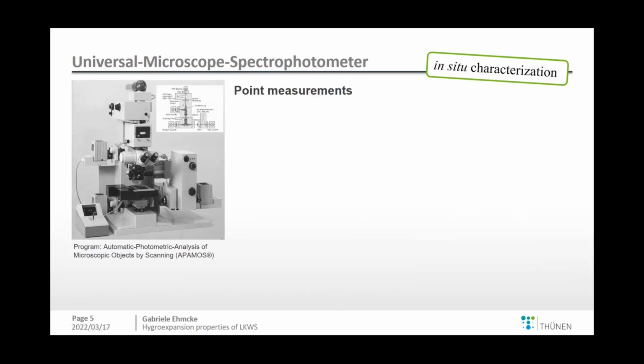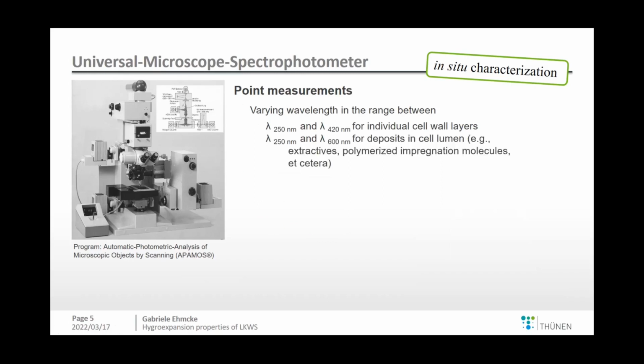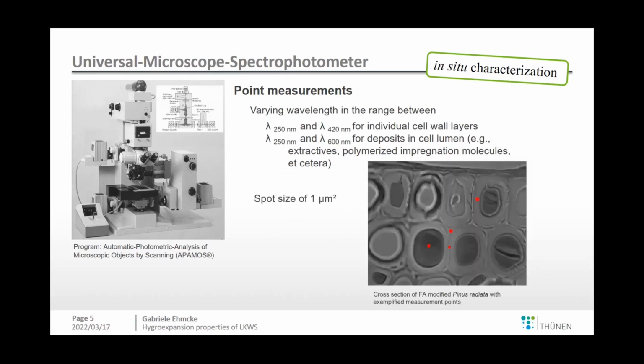Another tool is the point measurement. So we can look at individual cell wall layers. Here we use varying wavelengths in the range between 250 and 420 nanometers for the cell walls. And when we want to look at extractives or other things within the parenchyma cells, for example, then we choose a little bit higher wavelengths, up to 600 nanometers, to get all this information in the wood.